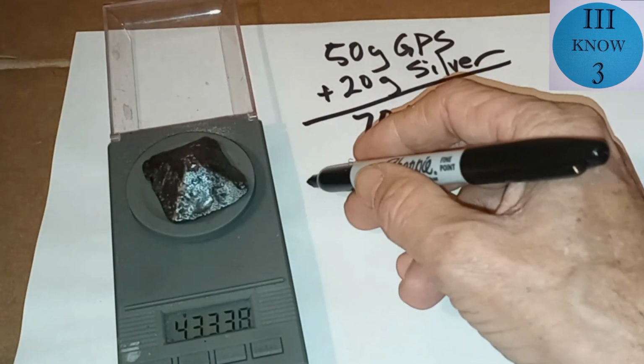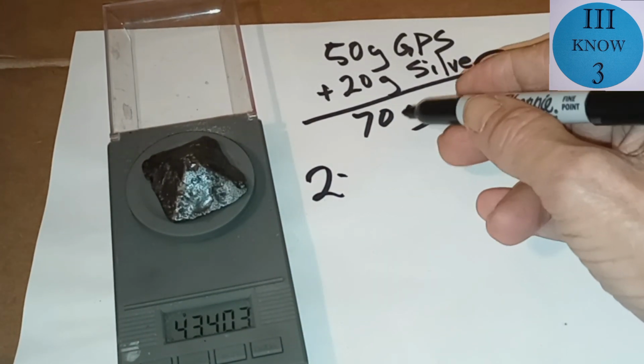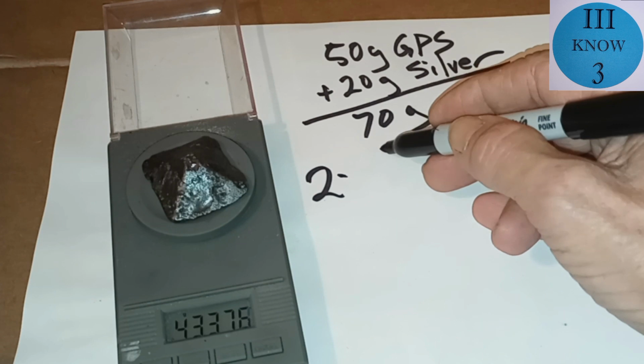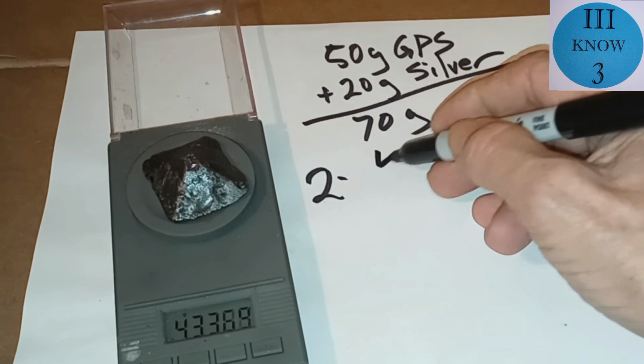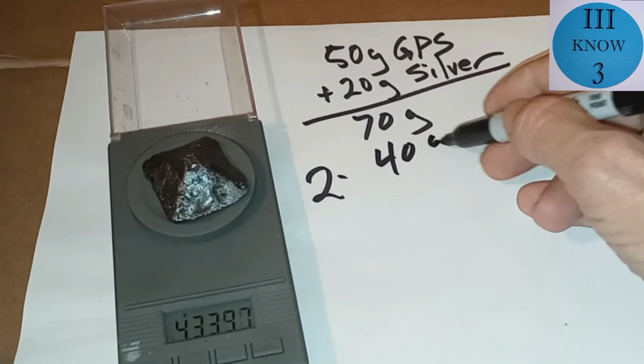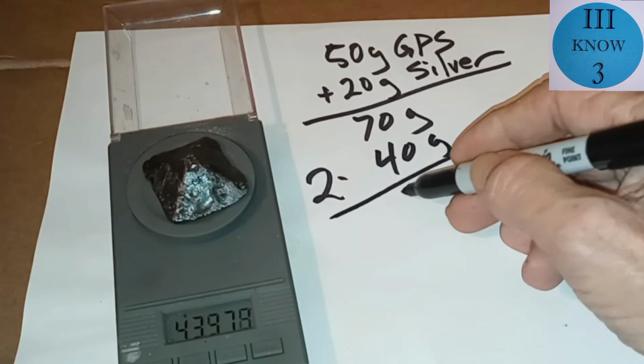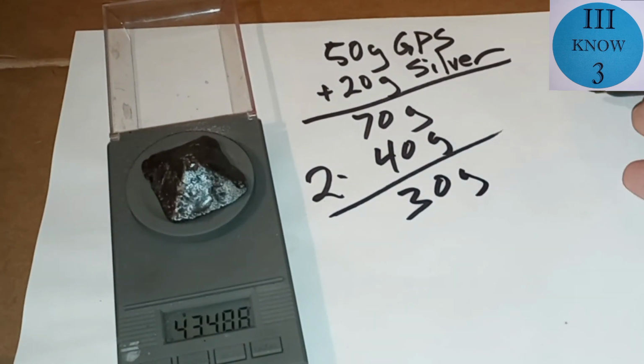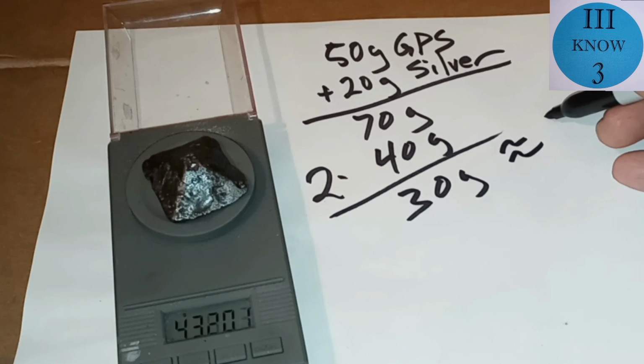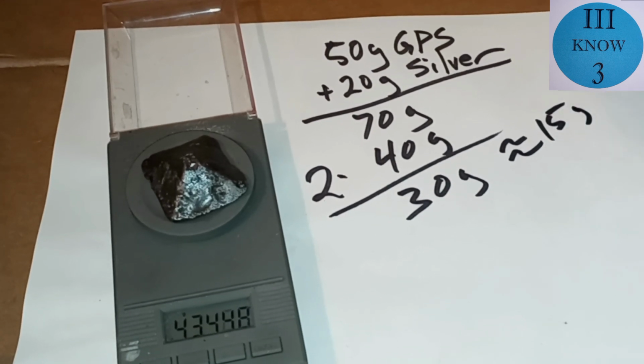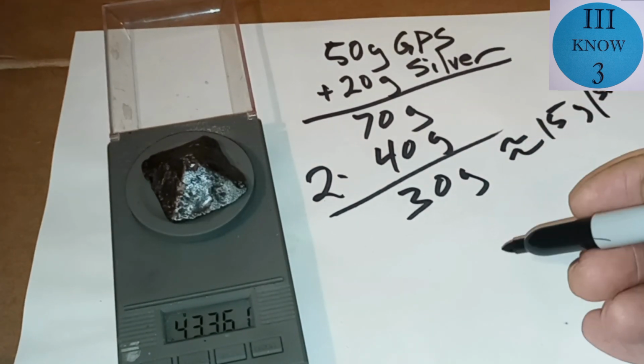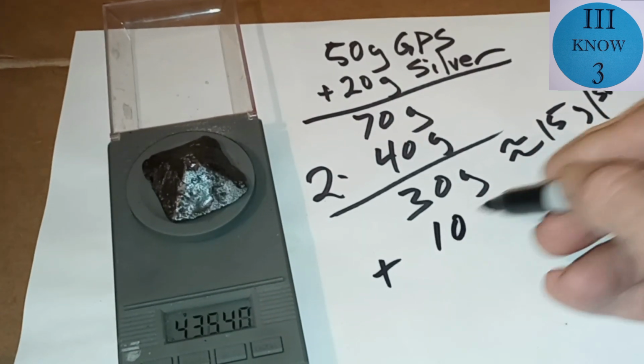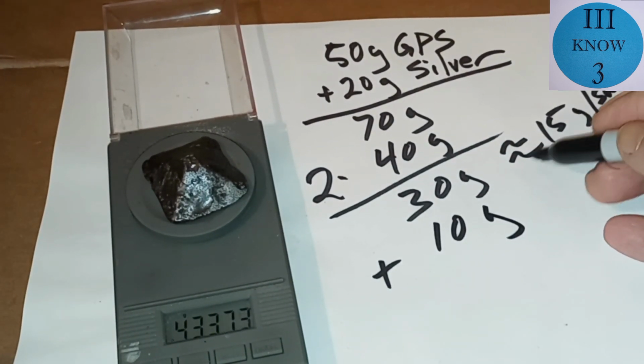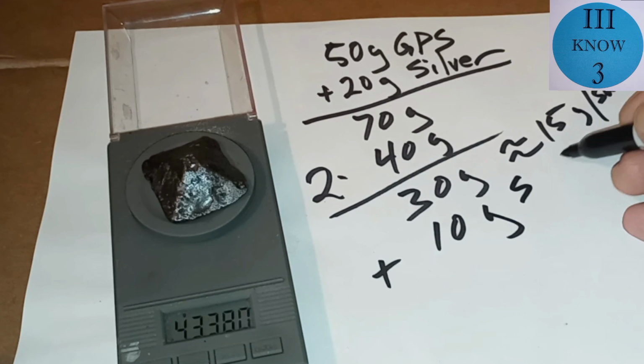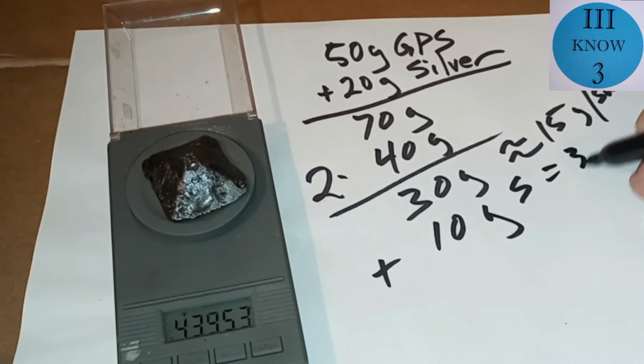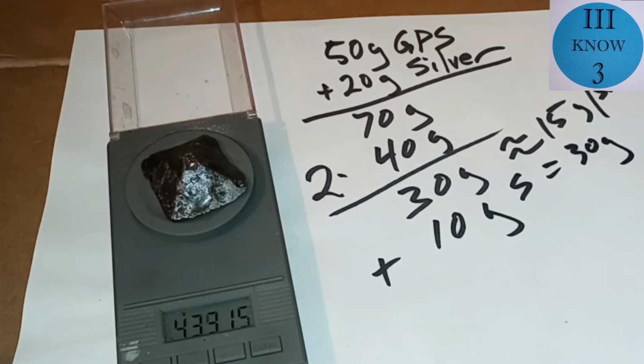After the first 2 smelts, we were left with, it was like 39 point something grams, so we're just going to call that 40 grams left. So if you subtract that, that gives us 30 grams, which means that we took out about 15 grams per smelt. After that, we added 10 grams more of powdered silver, which would give us a total of 30 grams of silver in the batch.